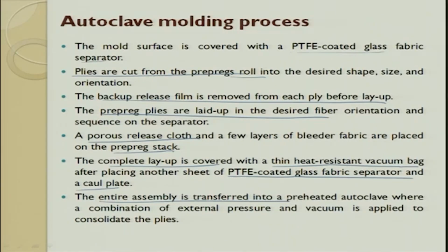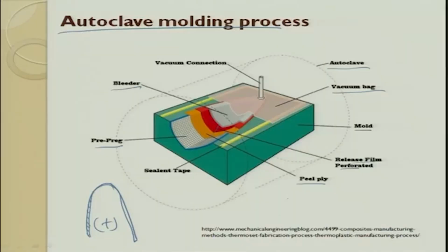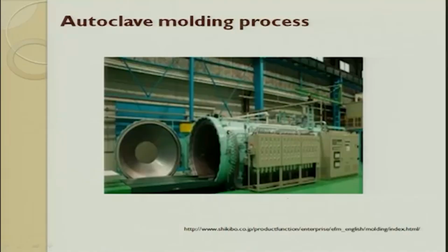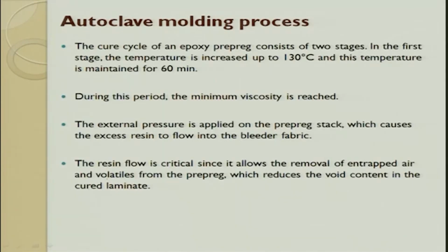Today there are companies which make the complete race car body through this. They make a pattern and then use all these procedures. So this is as light as possible, and it can be made with very high drag reduction. The efficiency goes very, very high, and these are all made out of carbon fiber composites. So you can see an autoclave. This is a real autoclave. You put the component here and then it is moved inside the shell, and then you lock it so that you create the necessary pressure and temperature.